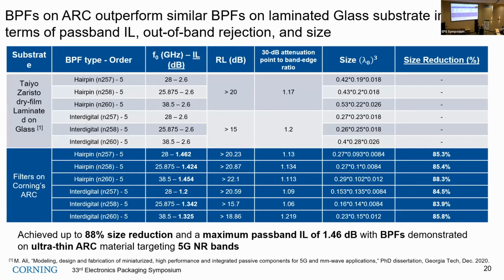In a nutshell, this is the comparison chart of the incumbent, dry film laminated on glass, versus filters fabricated on Corning's ARC. Especially, we are looking at the insertion losses. ARC shows very low loss compared to the dry film laminated on glass substrates. And we reduced the size by up to 88% from the actual physical size of the filter. Both the insertion loss and the size show superior performance for filters fabricated on ARC for the 5G NR bands.